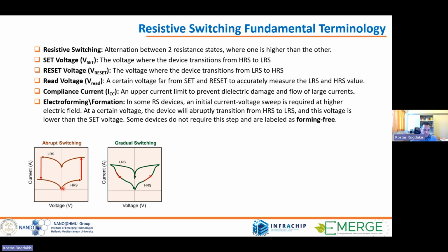Actually, when you start from, let's say, 0 voltage, you start from a high resistance state, what HRS means, it's high resistance state. And when you cross a threshold voltage here, you jump to a low resistance state. So then the device, if you go back, remains in the low resistance state until you go to a negative polarity. And then if you exceed this threshold, the device will go back to high resistance. So this loop is a typical switching loop, and a memristive device has two states, high resistance and low resistance. So you can use it as a memory, but also you can do computation using this kind of memristive devices.